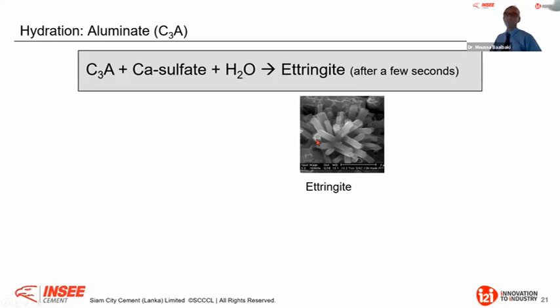Therefore, the main product is ettringite, and ettringite forms after just a few seconds. It's a very important cement hydration product, because the ettringite will later control the dissolution of all the ions we need to start to precipitate and keep the hydration going in a normal way to pursue its development. Otherwise, if we don't form ettringite, we will form some calcium aluminate hydrate, and this will stop some dissolution.